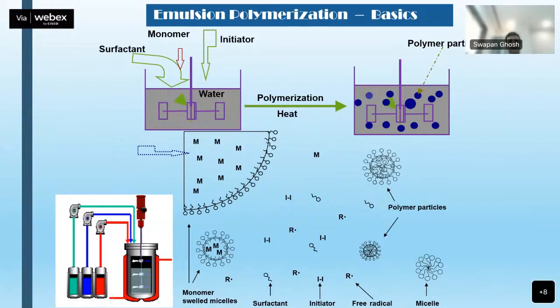Second step is once the initiator is inside this hydrophobic zone, they do not love this zone because they would like to come back to the water, which is a stable zone for them. They are soluble there. So the moment an initiator, that means a radical, enters the particle, it stays there for some time, and it comes back. The longer it stays, the larger the polymer chain will be.